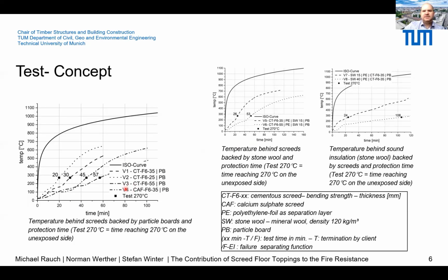You can see that the calcium sulfate screed with a thickness of 35 millimeters has a protection time of 45 minutes compared to a cementitious screed with a thickness of 35 millimeters, which has a protection time of 30 minutes. You can also see the horizontal plateau of the calcium sulfate screed where the water of the gypsum evaporates. This leads to the longer time for reaching the 270-degree criteria.